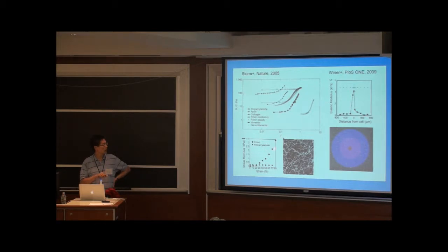Now, the reason why these biological polymers are not linear, for the most part, is because they're filamentous, semi-rigid materials. So this is a SEM of fibrin. So a cell might be sort of this big. Okay, so you can just sort of imagine that you have all of these filaments. The filaments are fairly inflexible. They don't extend very well, but they bend very easily, right? Because they're thin materials.